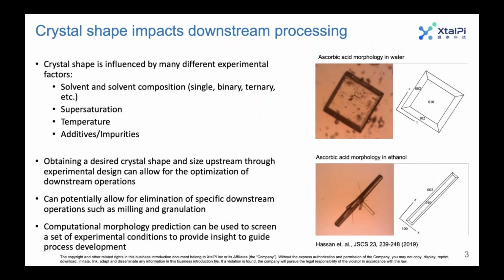But we know that the crystal shape is influenced by many different experimental factors. So you can deal with the crystal morphology either through crystallization itself by tuning experimental variables, or you can use those downstream processes like milling or micronization. There are a number of advantages to trying to improve the morphology through the experimental variables. And I'll just give you an example. On the right here, we have ascorbic acid grown in water, where it forms these square or plate-like crystals, versus ascorbic acid in ethanol, which forms these needle-like crystals. So just by changing the solvent, you can get a much better, preferable morphology, which could help with your